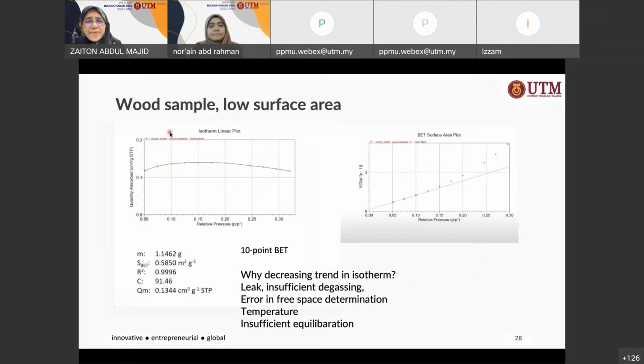A wood sample, which also has low surface area. Look at the isotherm plot. They look only at the 0.05 to 0.3 range. It is decreasing, which is not right. The uptake should increase with increase in pressure. Right now you have it decreasing. And then when you run the BET transformation plot between 0.05 to 0.3, notice the deviation from linearity beginning at 0.15. So what they did here is a 10-point BET plot. There is a deviation from linearity beginning at 0.15 relative pressure, P over P naught.